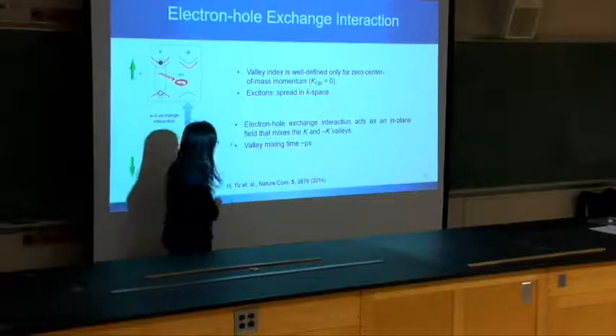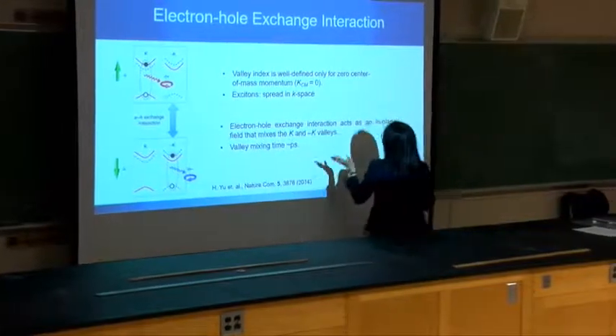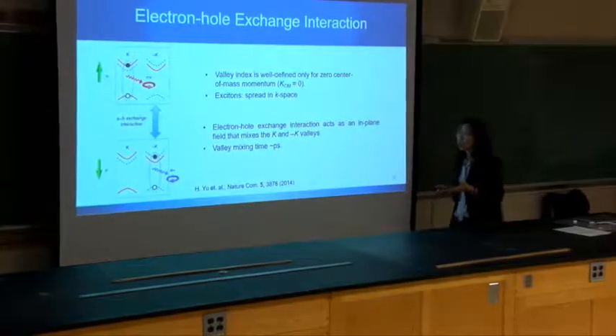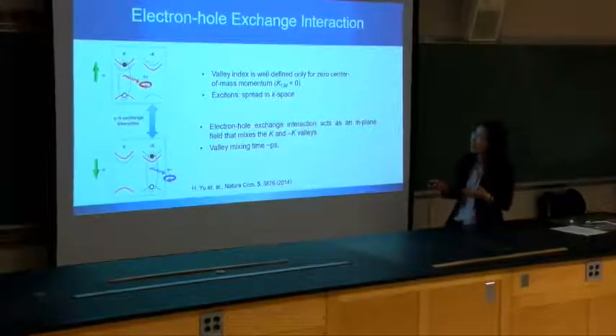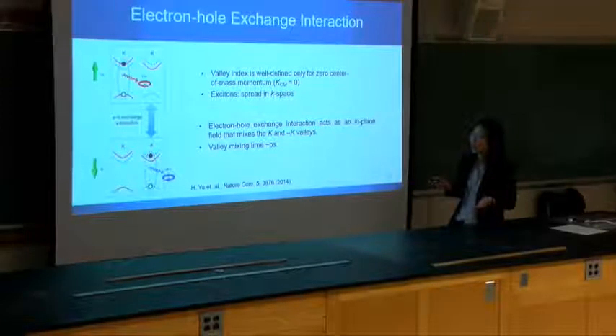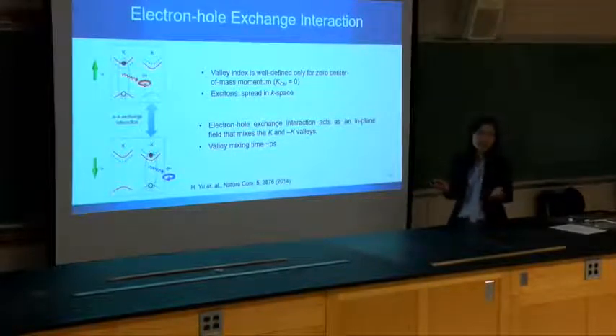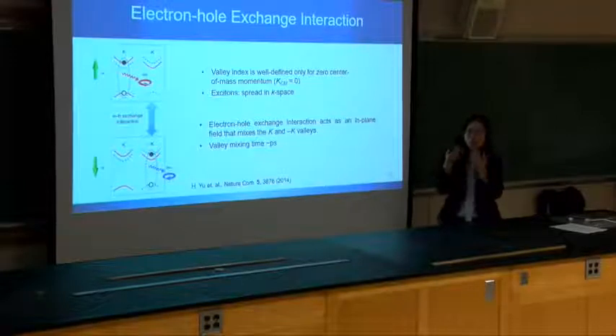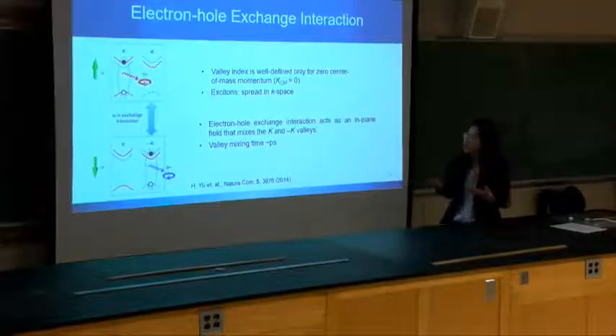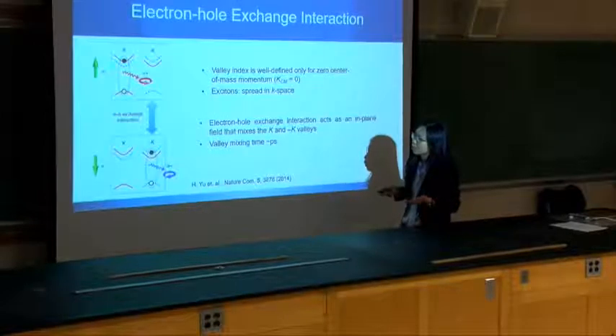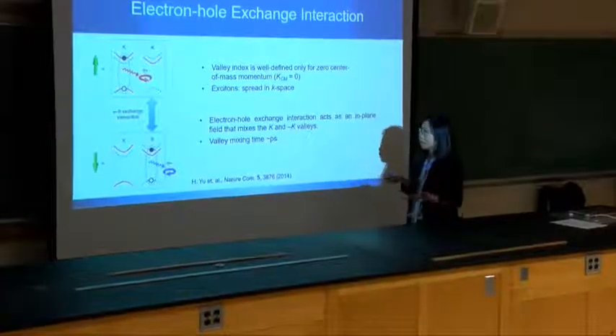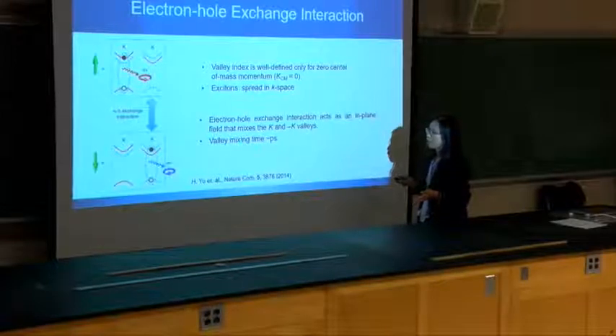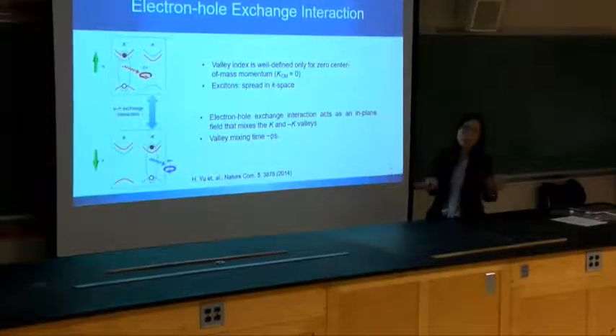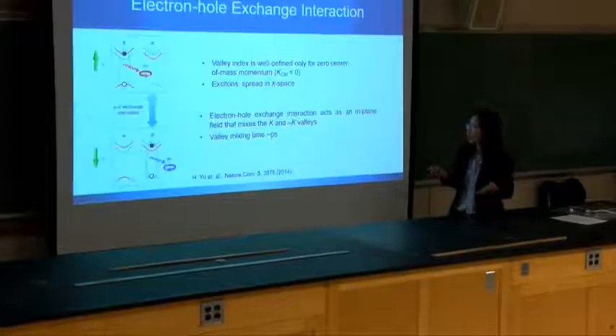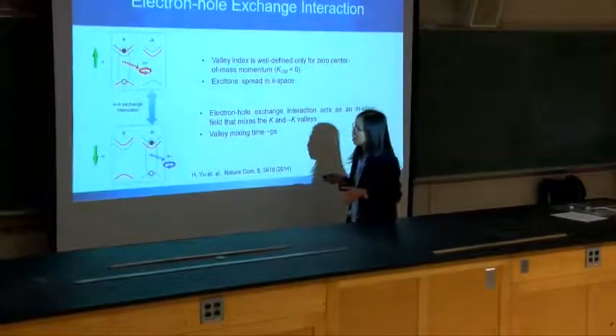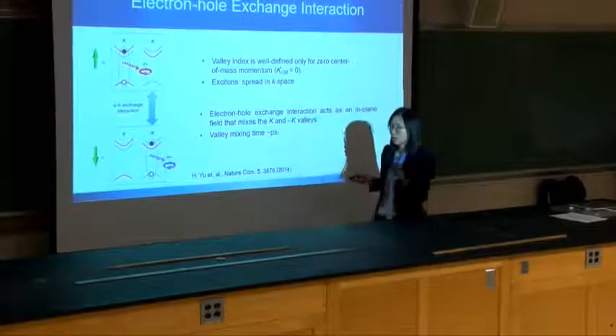And in this case, as the exciton has a finite center of mass momentum, it will see the electron-hole exchange interaction. And this exchange interaction will act as an in-plane field that mixes the two valleys. So in other words, when we initialize the system in whatever way, optics or electronics, if we probe the system after the valley mixing time, the information will be lost.